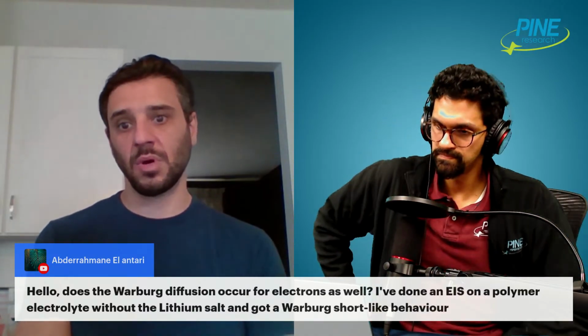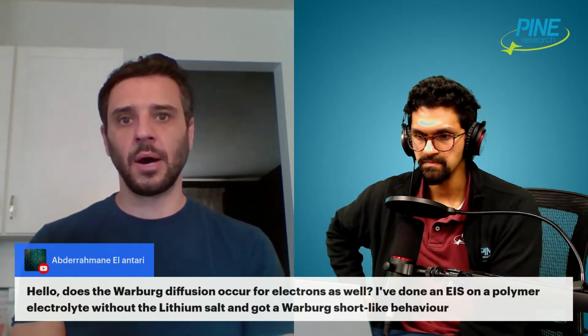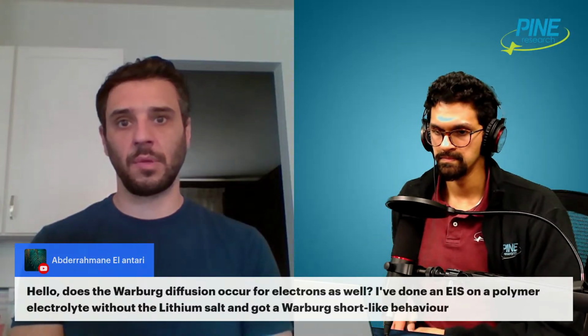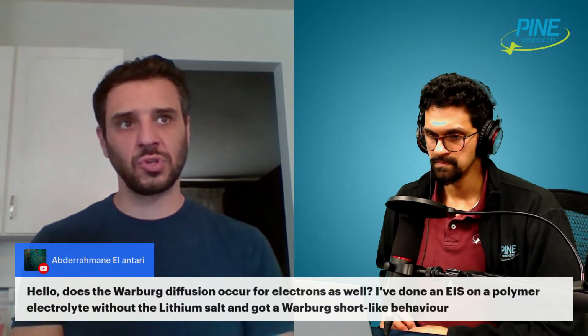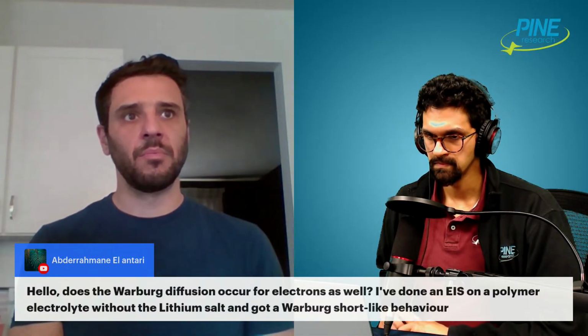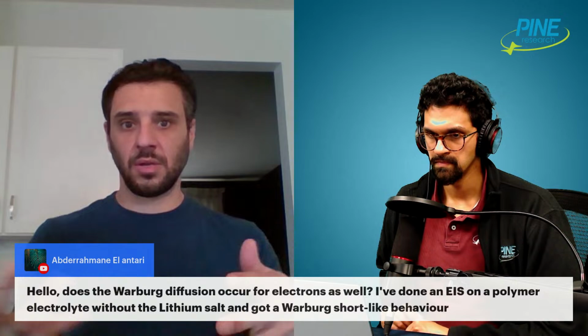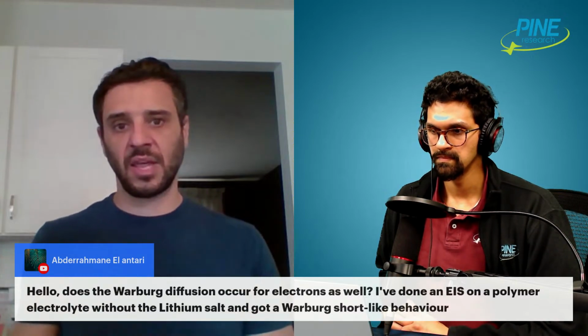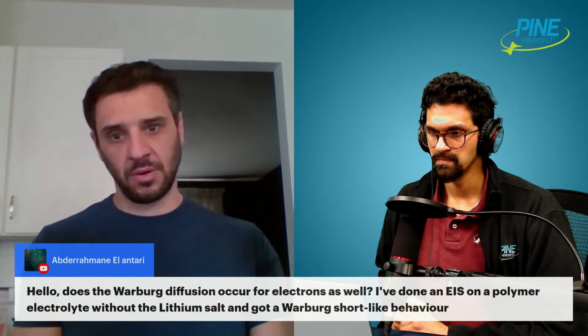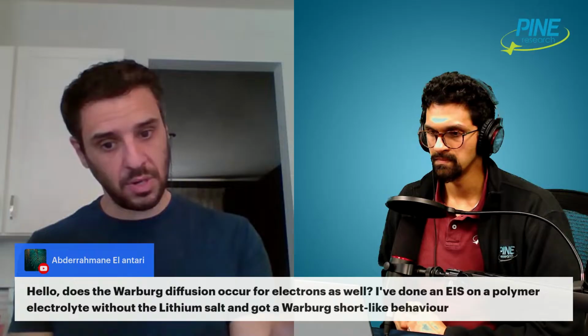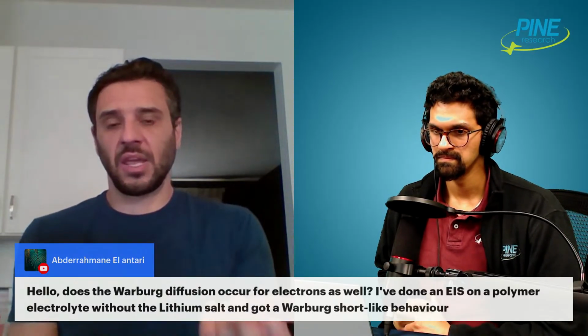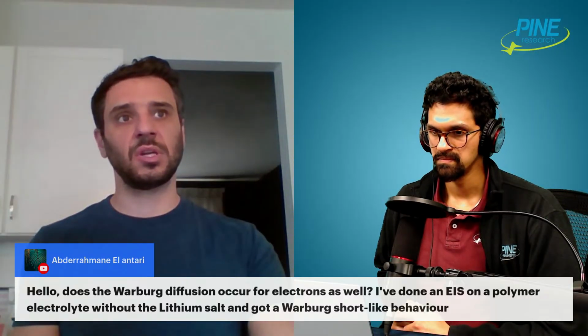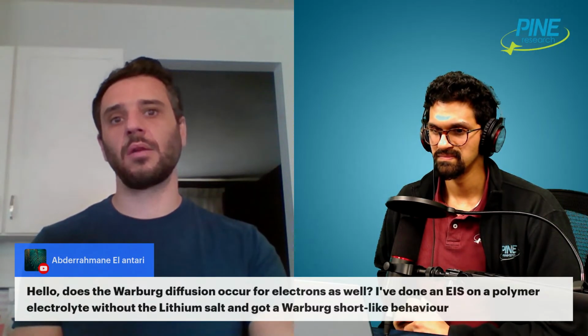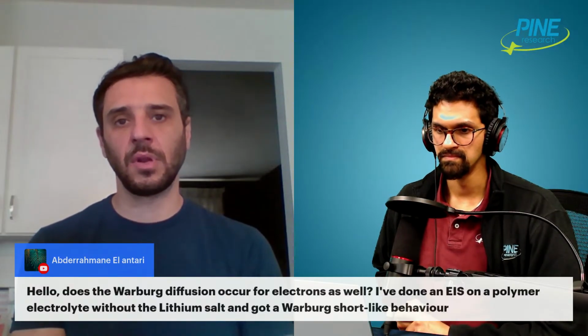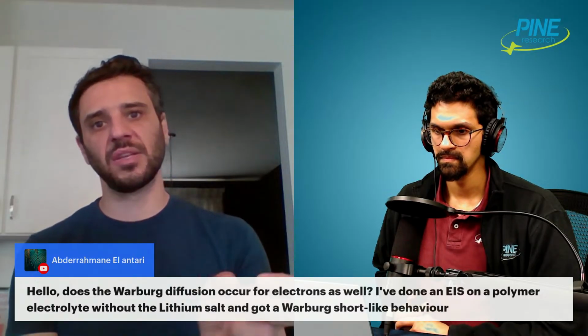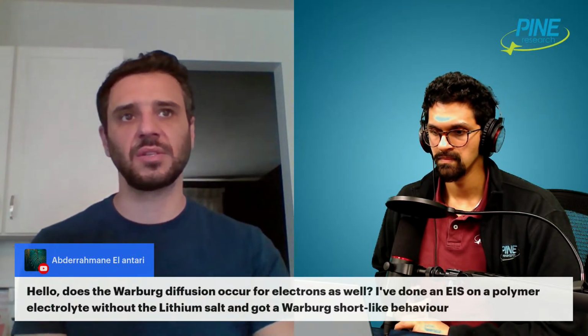And in reality, it might be giving you some really good information about the diffusional behavior of your electrodes themselves, or the membrane itself, and precisely where the diffusional path is. I don't know, obviously, but there's diffusion happening somewhere, and if you have a Warburg short, it's indicating that you have a fixed length of diffusion. Again, whether it's in the polymer electrolyte itself or the electrode pores or something of that nature, and you're getting information about that. So there's still value in that kind of data, I would say, even apart from having the lithium plus to do the Faradaic charge discharge kind of processes.